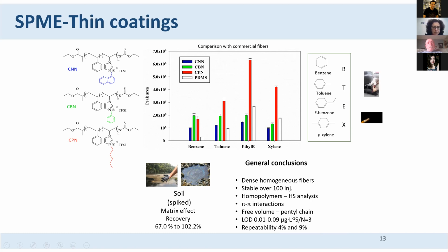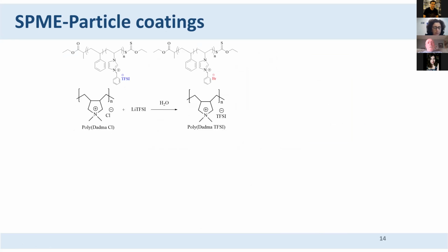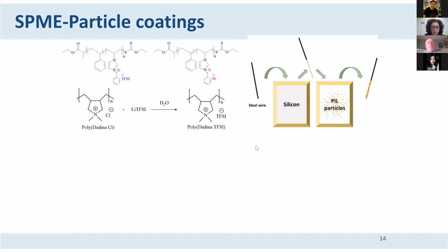However, in the thin fiber, what we realized is that it was very thin. And so we would like it to have a high surface area so that we don't have to expose our fiber for a long period of time to the sample. And so we went back to those polymers that we had worked with in the thick and the thin fibers. And David always had these great ideas. He just came up with this idea that it was very simple: just grind the polymers and use silicone to coat our fibers.